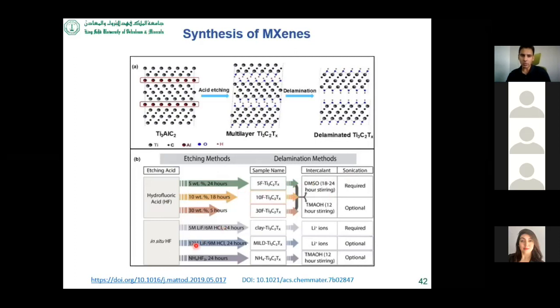So the latest development is we can use in situ HF techniques, where you are not using HF directly, but you are using LiF and HCl, and HF will be produced inside the solution. Okay, and it will etch or remove the aluminum layer. Okay, and later on after sonication, the sheets can be dispersed. So again, there is potential in this area, especially for the chemistry people.